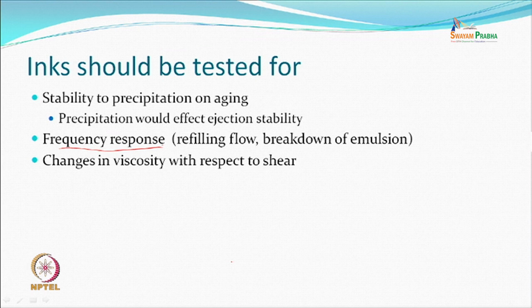How does the liquid respond? When something goes out, something must come in at the same amount. If it does not, if more goes out and less comes in, then you have various kinds of issues. So it is tested on frequencies of the refilling flow and breakdown of emulsion. Everything may look right in a static condition, but the dynamic condition may not be right.